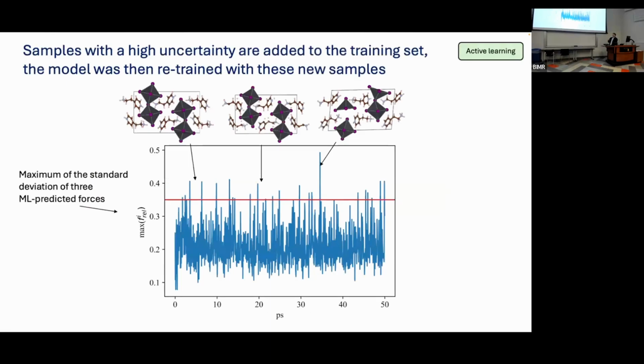In terms of the active learning loop, the way we anticipate where the model might fail is through uncertainties. And in this case, we train a committee of models. So we have 3 different machine learning potentials that have been trained independently. And we apply them in an MD simulation. So this is the 3 models being applied in the MD simulation to the same configurations over and over.